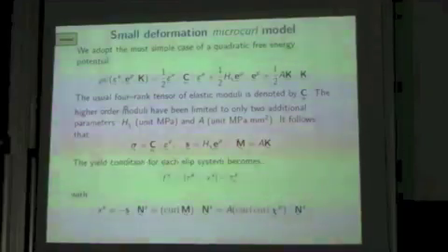I could introduce more, but for this example I take simply one single parameter A here for the energy, and one H chi for this contribution here. If you take the derivative, you get the stress. You get generalized Hooke's law, where you have the double stresses proportional to K, in fact, with this material parameter. Okay, this is the first assumption, a simple case.